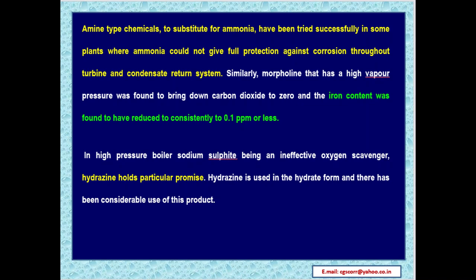Amine type chemicals to substitute for ammonia have been tried successfully in some plants where ammonia could not give full protection against corrosion throughout turbine and condensate return system. Similarly, morpholine that has higher vapor pressure was found to bring down carbon dioxide to zero. The iron content was found to have reduced consistently to 0.1 ppm or less. In high pressure boilers, sodium sulphite being an ineffective oxygen scavenger, hydrazine holds particular promise. Hydrazine is used in hydrate form, and there has been considerable use of this product.